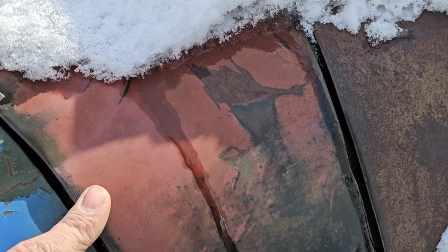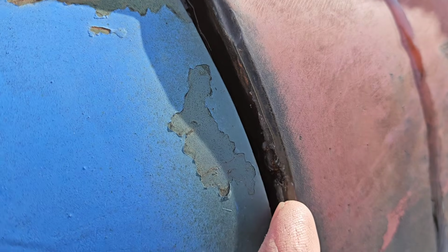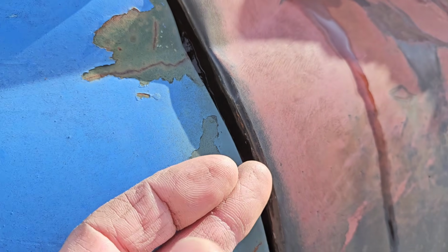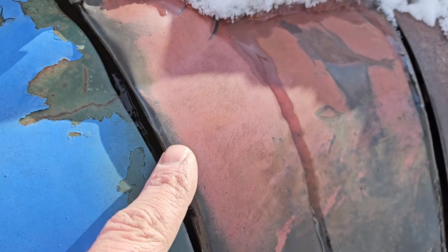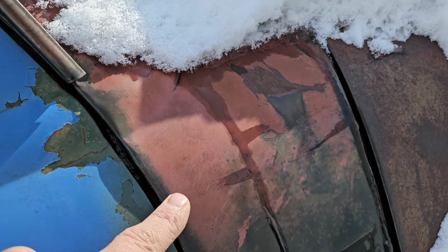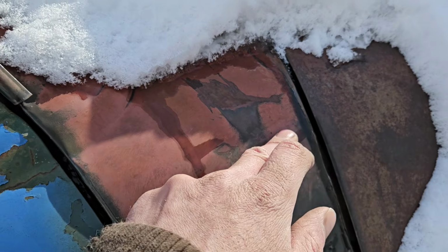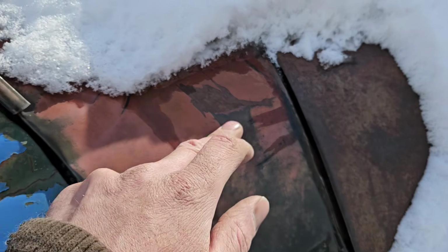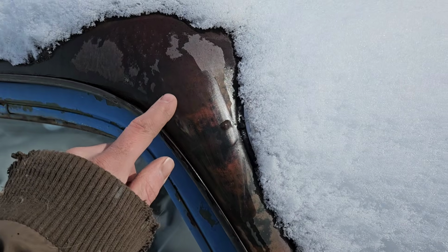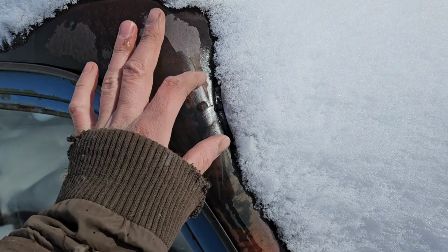but this still has the lead in it. If you look closely here, we can actually see rust starting to come through from below that seam. And if we had melted out all the lead here, I guarantee there would be rust all through here along this lap weld. Here we have another seam on the A-pillar.